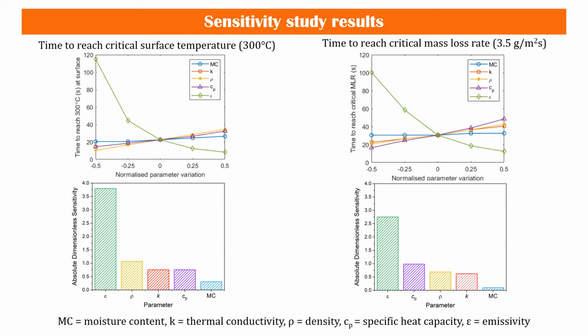The figures on the left showed that the time to reach the critical surface temperature was most sensitive to emissivity, followed by density, thermal conductivity, and specific heat capacity. The emissivity governs the heat flux absorbed by the wood, thus increasing emissivity decreases the ignition time.